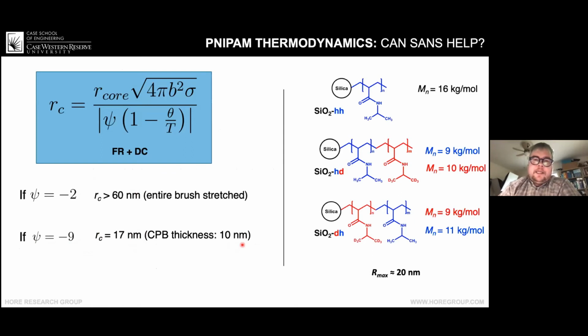So we did the same thing that we did with the polymethyl acrylate. We synthesized deuterated NIPAM monomer and then polymerized it. So we have a sample with just a normal brush, and then the isotopic block copolymer, and we chose these molecular weights so that if they were fully stretched, the length of the entire brush is about 20 nanometers.